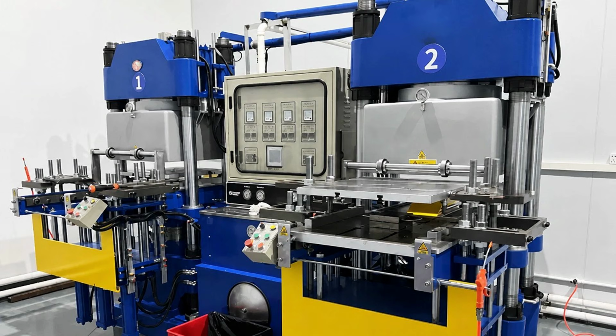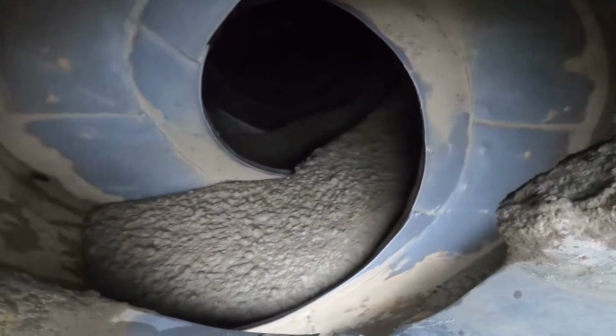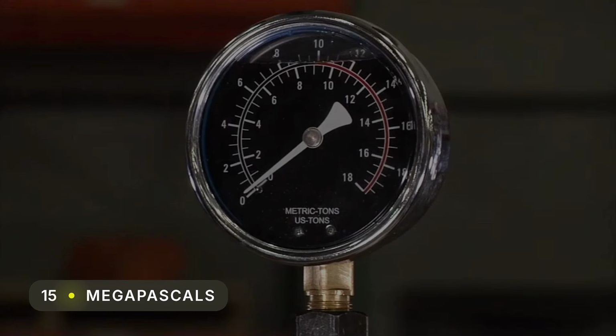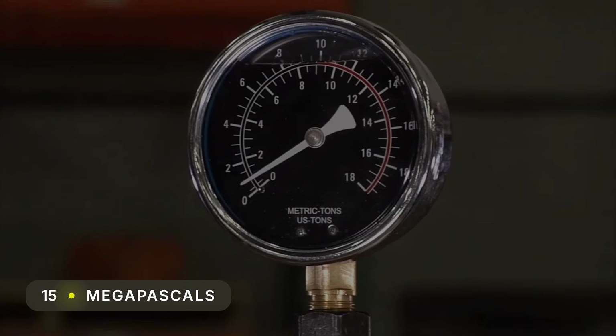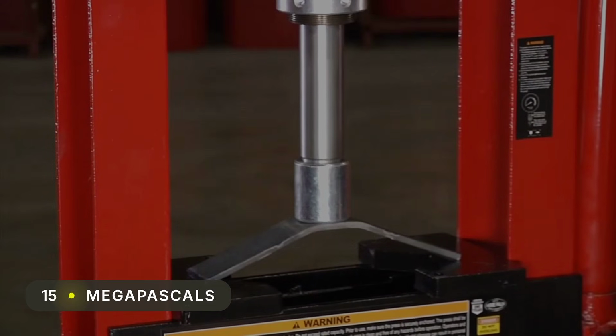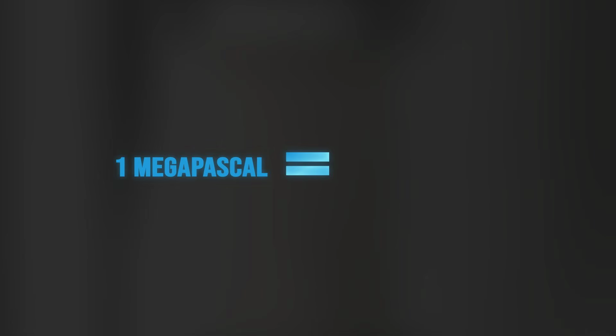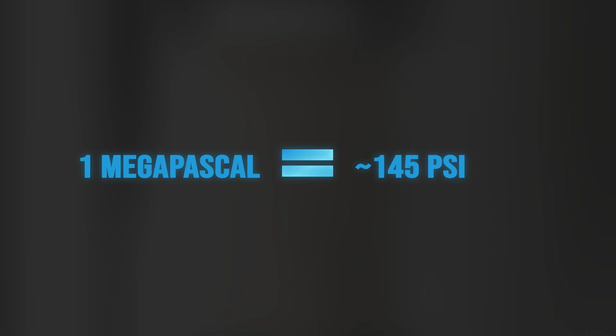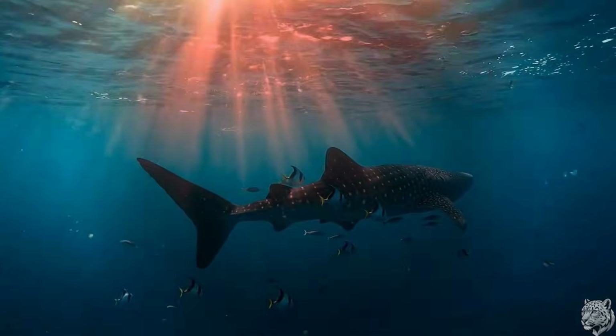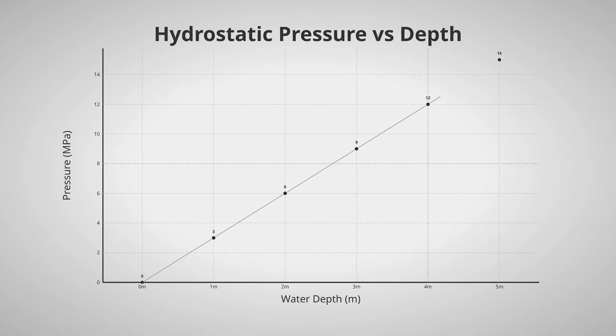The process is called compression casting. Fresh concrete, mixed to standard specifications using standard cement, standard aggregate, and standard water, is placed into a hydraulic press and subjected to between 5 and 15 megapascals of applied pressure while still in its plastic state. 1 megapascal is approximately 145 pounds per square inch. The pressures used in compression casting are, at the upper range, equivalent to the force at the bottom of a column of water 1.5 kilometers deep.